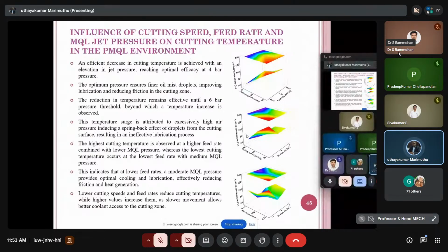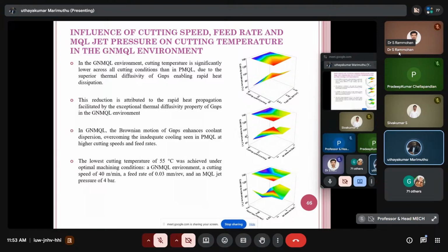This indicates that with a lower feed rate, a moderate MQL pressure provides optimal reduction of friction and heat generation. Lower cutting speeds and feed rates reduce cutting temperature, while higher values increase it, as slower movement allows better cooling across the cutting zone. Here you can see the influence of cutting speed, feed rate, and MQL jet pressure on cutting temperature in the GNMQL environment.